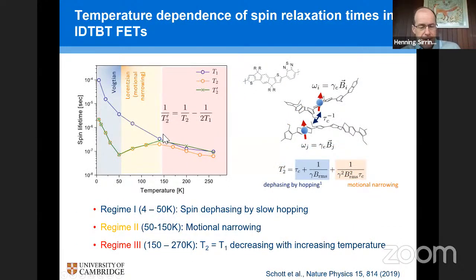At around 150 Kelvin, T2 goes through a maximum here, and then it decreases again as we go towards room temperature. So clearly at 150 Kelvin, this motional narrowing regime stops and something else is kicking in. And this something else took us a while to figure out. It's not expected. We had expected the motional narrowing to become more and more effective as we increase the temperature, because the charges are moving faster and faster in these polymeric systems. The carrier mobility in this polymer system is thermally activated, so transport becomes more and more effective towards room temperature. But still, that's not what happens with the spin relaxation.